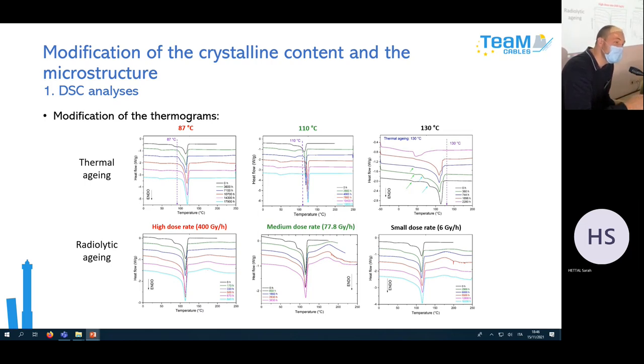And if you have any kind of these defects, well, you will for sure decrease the crystalline content of your material. So if you age your sample at 130 degrees C, you are 100% amorphous, you do oxidation and you incorporate oxygen, and you decrease the temperature so that it crystallizes, well, obviously you will have a change in the crystallinity ratio. But if you do the same aging at 110 degrees C, the first crystals that exist in the material are not molten during aging. And the crystals remain CH2. So the only thing you can do is create a transition process and increase the crystalline content in your material, but that's it actually. So it's completely different. Actually, it depends on the local properties of the material. Yes, if we have defects or whatsoever. Yes.